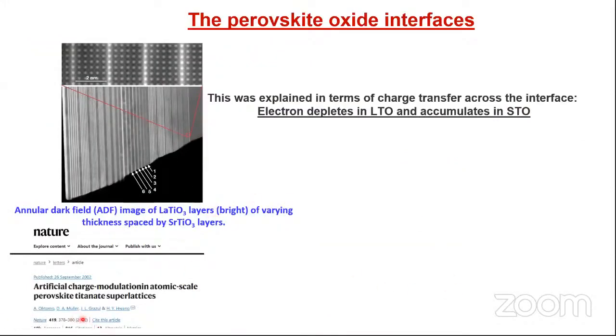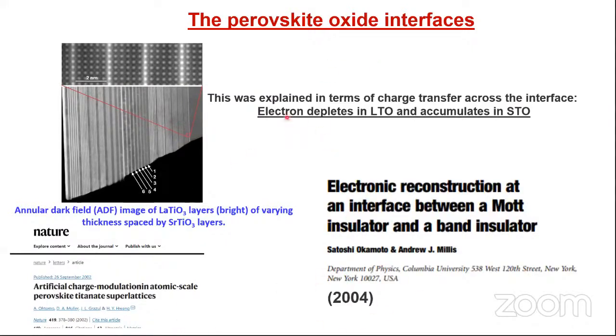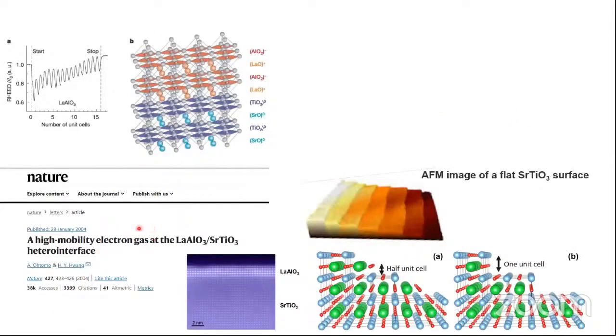The story began in 2002 when superlattices between LTO, lanthanum titanium oxide, and STO, strontium titanium oxide, were made. And it was seen that the interfaces between these materials became conducting. They in fact formed two-dimensional conducting electron gases. The explanation came in 2004. It said that charge transfer from LTO to STO causes the formation of such a two-dimensional electron gas, which is conducting at the interfaces between two insulators. But the same group discovered another high mobility electron gas at LAO-STO interfaces, where LAO is lanthanum aluminum oxide, and this came in 2004.